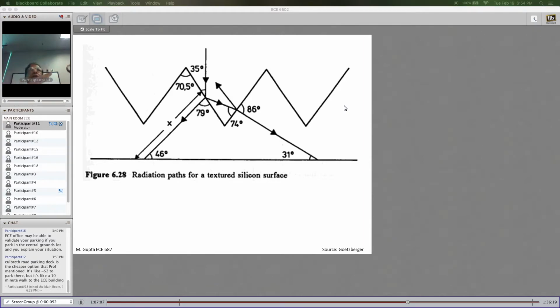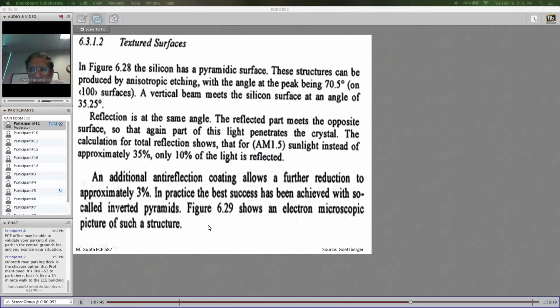They etch one crystallographic orientation differently than the other. So 100 could be etched at a different rate than 111. And the 111 plane is what the 70.5 degrees comes from. So what happened is when you etch it, you lost that 100, but you created that 111 plane. So that 70.5 degrees, or 35 degrees, comes from that crystallographic orientation.